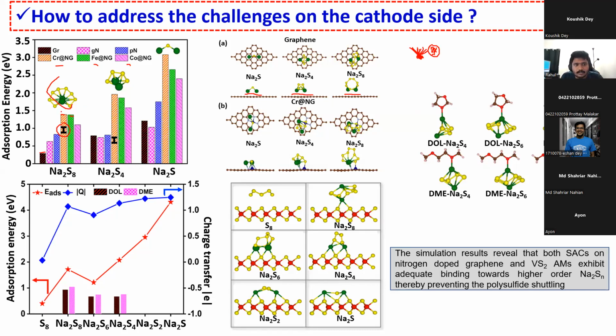Now, when we talk about the single atom catalyst, you can see clearly that there is bond formation. This is sulfur, this is sodium. There is a strong sulfur-transition metal bond, as well as a sodium-nitrogen bond. Because of that, the chemical interaction is increasing, and as a result our binding energy increased. Basically we found that if we use this kind of single atom catalyst, we can trap the polysulfide rather than sending it to the electrolyte.